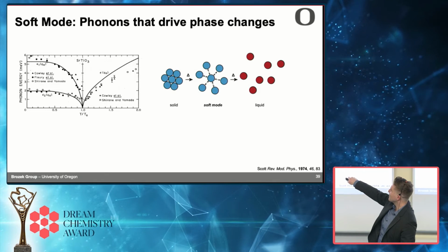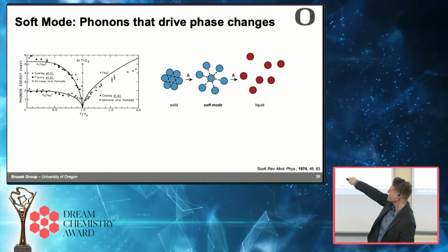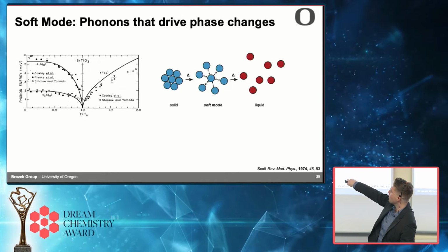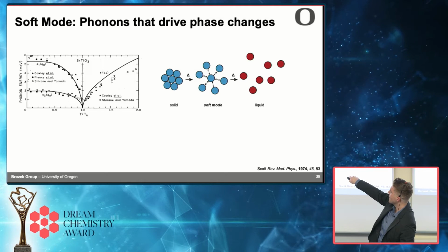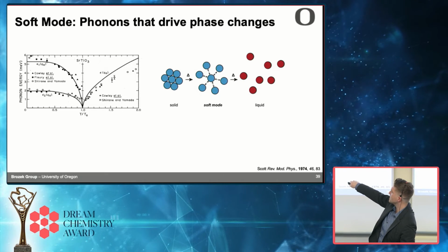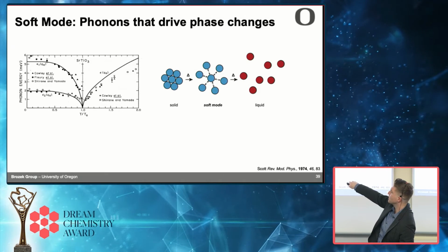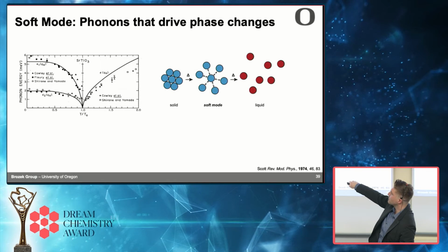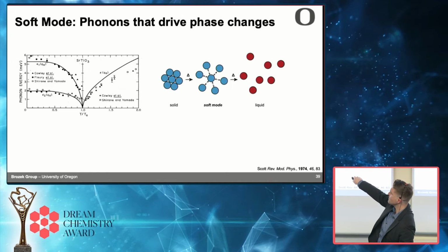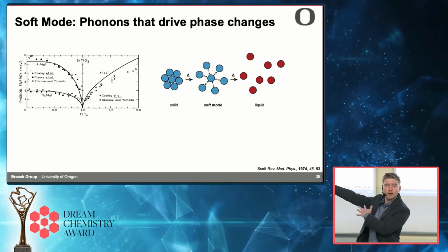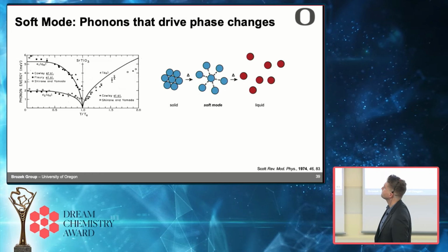And as you heat up the strontium titanate towards that phase change, you'll see that both of those phonons redshift until they disappear completely. The frequency goes to 0, and then above that temperature, they become a new phonon. They regain their frequency to become something else.